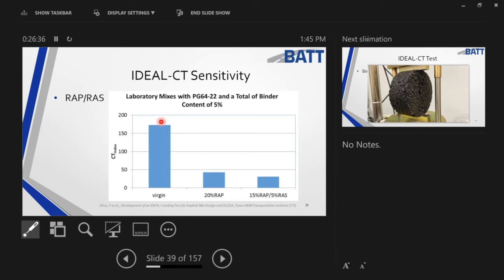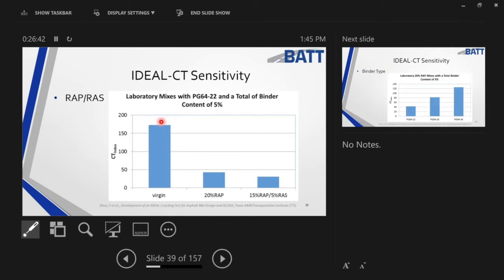but the aging or the extended heating of that mixture, conditioning, as it should be called, also will age the binder itself, which is important. And then thirdly, and very, very important, it releases the RAP. It releases the binder from the RAP or the RAS. You will not see that in 1 hour. You will not see that in 2 hours. But the more that you age it, the more you'll see that RAP release.